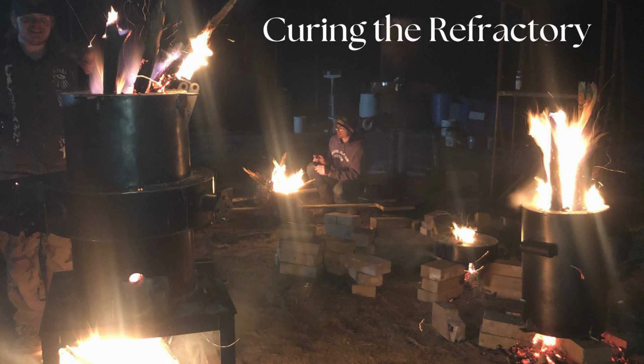So it does take several hours to complete, but it's necessary because if there is moisture, then that high heat will cause cracking and it will deteriorate much quicker, and you don't want that.